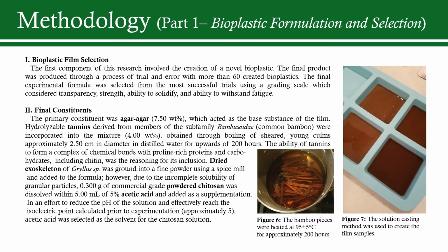After the tannin solution was the correct concentration, 0.3 grams of chitosan was mixed with 5 milliliters of acetic acid and then transferred to the tannin solution in order to dissolve the chitosan and bring the entire mixture to a pH of 5, which was the isoelectric point needed for the complex between the constituents to occur. 5 grams of agar-agar was added along with 0.1 milliliters of glycerin, and the solution was thoroughly agitated.